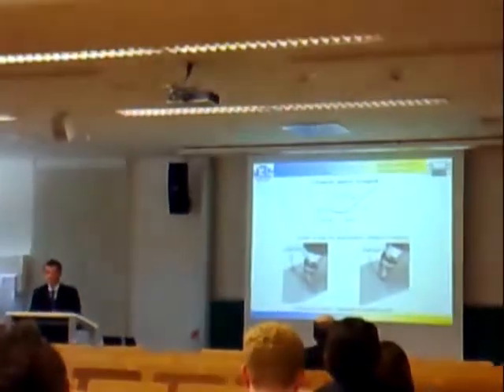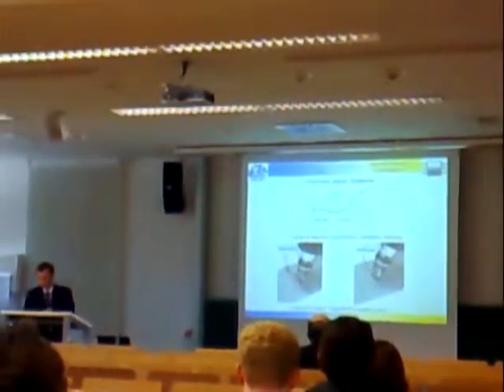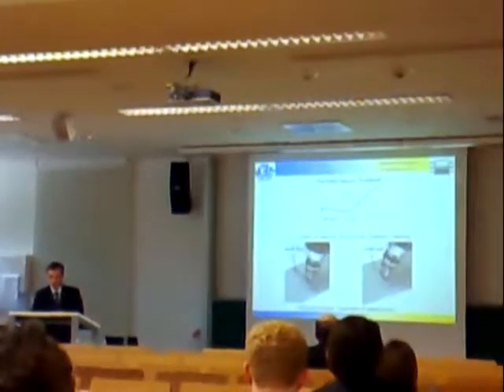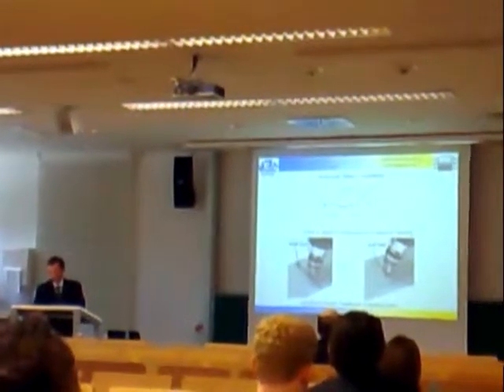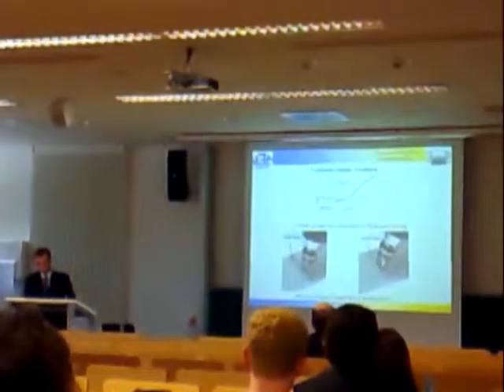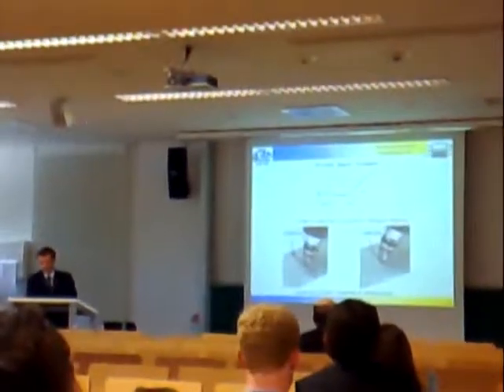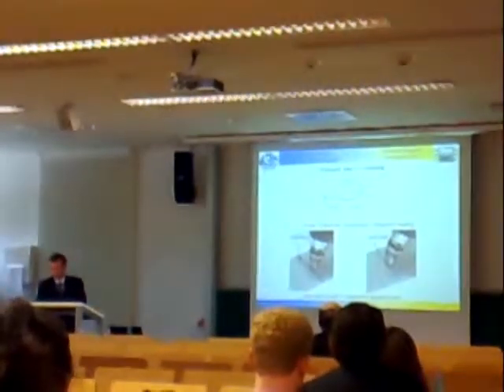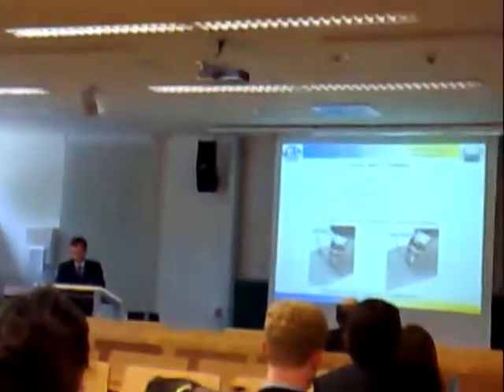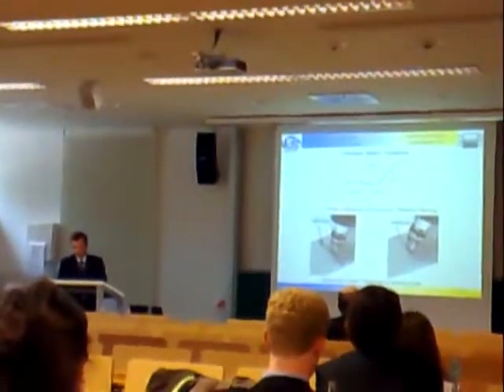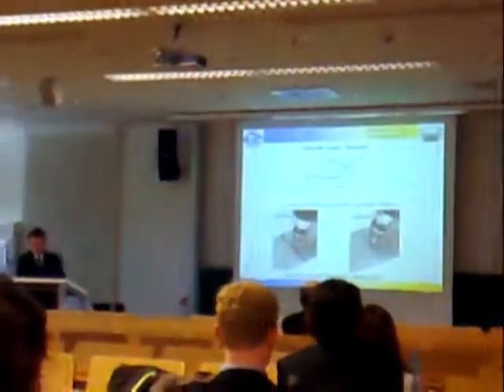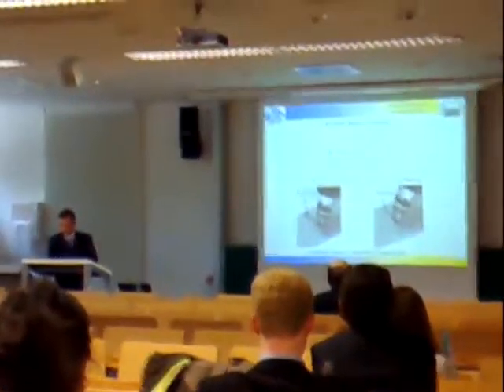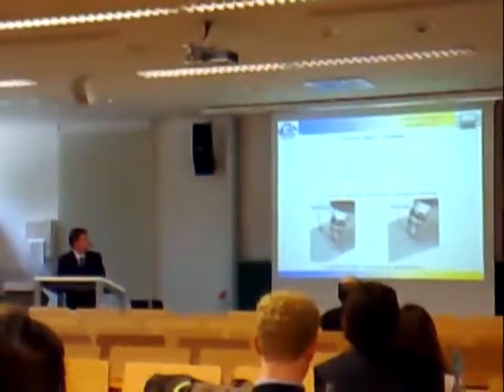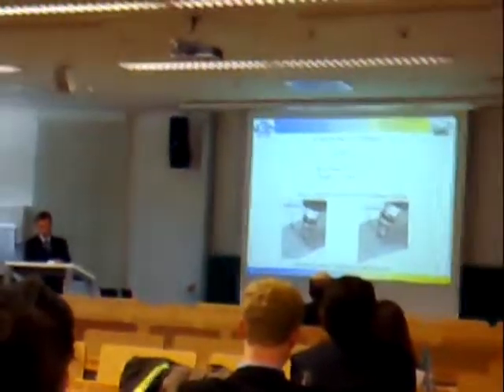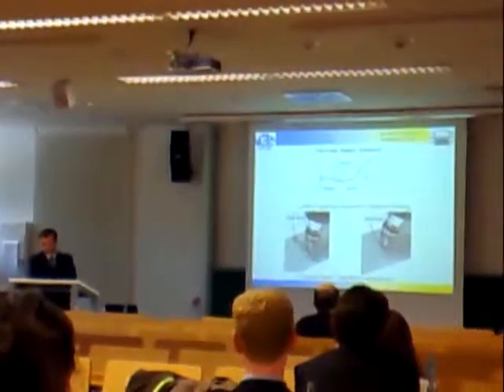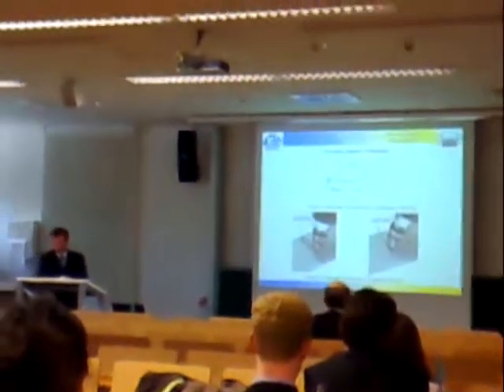The beneficial effect of ultrasonic peening is achieved mainly by relieving harmful tensile residual stress and inducing compressive residual stresses in the surface layer of metals and alloys, decreasing stress concentration in weld zones and enhancing mechanical properties of the surface layer of the material. Ultrasonic impact treatment was performed on both sides of fusion welded joints using the UP600. In this view you can see UP treatment, face and root respectively.